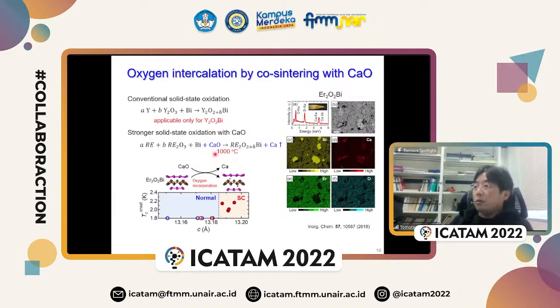So we use calcium oxide as a new oxidant. This is indeed a strong oxidant. By mixing in the calcium oxide, it oxidizes the compound by introducing excess oxygen, and the calcium metal is gone by evaporation. This is schematically shown in this figure. So the calcium oxide is used for oxygen intercalation for the various layered oxide bismuth compounds.